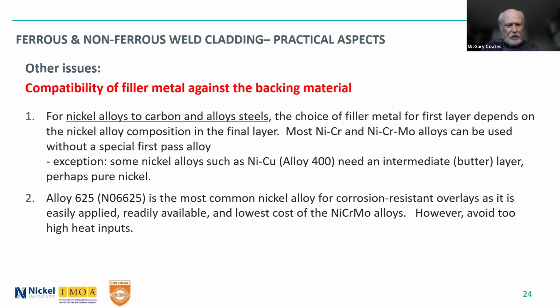I remember a case where a fellow in Canada did an overlay with 625. He used the submerged arc process. He had a flux that welded beautifully, but it gave hot cracks. With submerged arc welding, you really want to do a lot of high production, and the cracks didn't open immediately. So you do your layer, you examine it, there are no cracks there, but cracks will form later as the stresses relieve themselves. And he had to do the whole job over again. So yes, 625 is common. It's relatively easy to use, but you have to be very, very, very careful with high heat input. You want to keep it as low as practical.